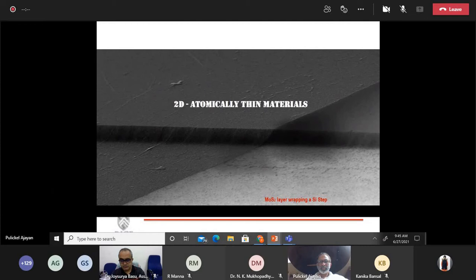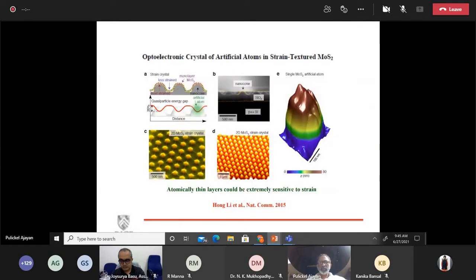And what is again quite challenging is the fact that such small perturbations in structure can lead to specific changes in electronic properties. So here is a very specific experiment where you wrap this molybdenum sulfide on a pre-patterned substrate and then use a scanning tunneling spectroscopy technique to understand the electronic structure of the molybdenum sulfide surface. And what you see is that at the tips where the stress is concentrated, the electronic structure actually changes and it becomes more metallic. So you can imagine when you're starting to put these 2D layers on substrates to make a device, all these blisters and wrinkles will have an impact because they will locally change the electronic structure. So it goes back to the same problem of intrinsic variability that you cannot really avoid in nanomaterials and nano-engineered structures because of the strong structure-property correlation that exists in these materials.